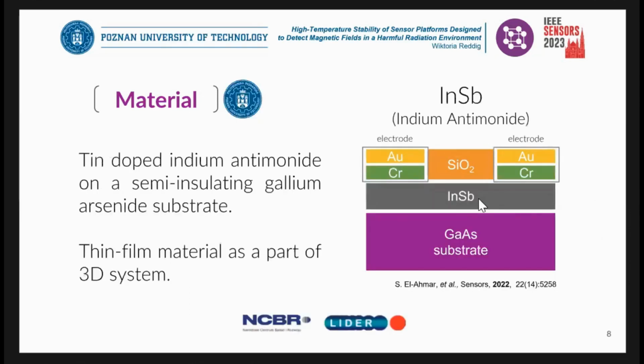The other platform is indium antimonide that is Sn-doped for better temperature stability. It is grown on gallium arsenide substrate and also has golden electrodes here with a chromium buffer layer. Here we have a thin film as a part of a 3D system. During the next presentation, there will be more about this material, so I won't elaborate on that now.